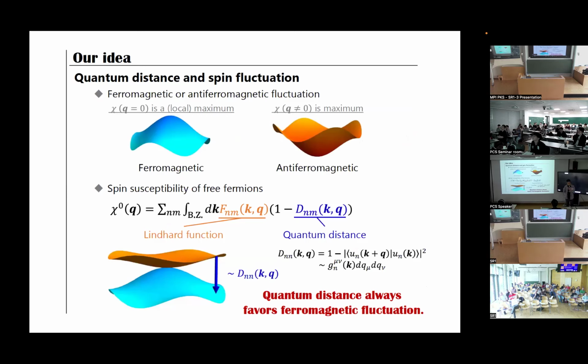In the following few slides, I will focus on the curvature of spin susceptibility in momentum space. This is related to ferromagnetic spin fluctuations and anti-ferromagnetic fluctuations. When the curvature of spin susceptibility in momentum space is negative, we have a chance to see ferromagnetic spin fluctuations. However, when the curvature is positive, ferromagnetic spin fluctuation is ruled out, and the spin fluctuation must be anti-ferromagnetic.